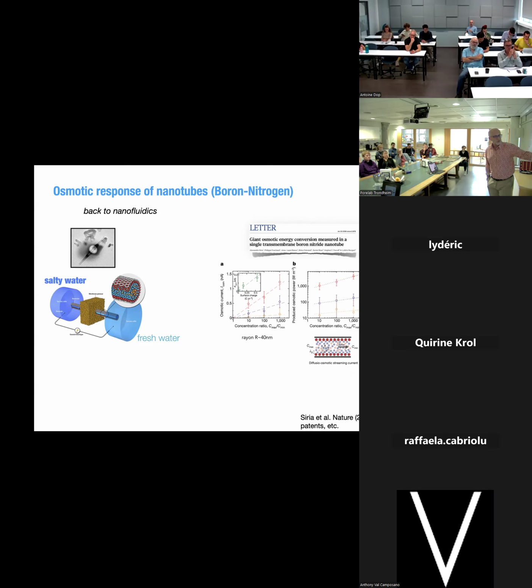If you convert it in terms of osmotic power, imagine putting a resistor outside and measuring the maximum power you can extract. You get a power in the range of 1,000 watts per square meter, with the idea that you put a lot of these nanotubes in parallel. If you multiply it, you would get a huge number. There are two interesting things there. First, at that time it was slightly unexpected to measure an osmotic current, because here the nanotube is very large, with a radius of 40 nanometers. So you shouldn't have any osmotic pressure, but you have a current.